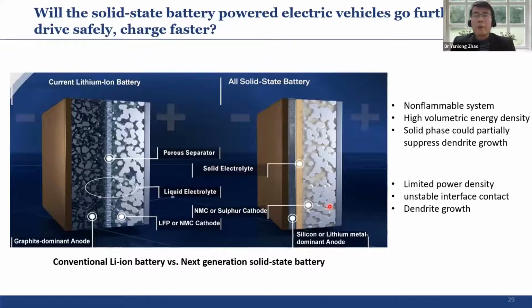From my point of view, I think it definitely can drive safely because you don't have a lot of flammable materials. But at the current state, we still have a lot of challenges to solve, especially the bad interface. Because of those interface issues, right now we can't use a high current density. Compared with traditional lithium batteries, the current density used in solid state batteries is still lower than in conventional lithium batteries, which means at the current stage, unfortunately, we can't see them charging faster.